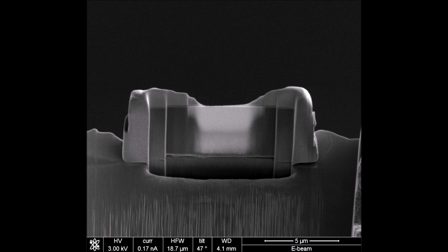Now, the fact that my specimen is by and large a piece of silicon is important, because silicon has certain characteristic behaviors when I interact a gallium ion beam with it. So the general catch-all phrase for that is what's called milling behavior, and if we want to summarize what that means, essentially it boils down to how fast can I remove material and how cleanly can I remove material, or after I remove material, what does my lamella look like morphologically, or the areas I've removed material from, what do they look like?